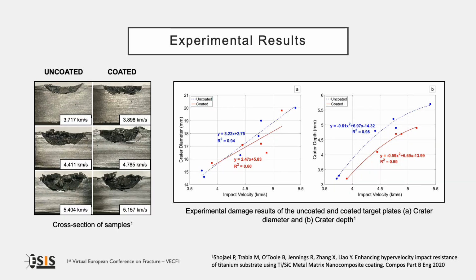The cross-section of the uncoated and coated specimen is reported in the figure on the left for different impact velocities. The crater diameter and depth was measured, and it is reported as a function of impact velocity in the diagrams on the right. Both the crater diameter and the crater depth increase if the impact velocity increases.